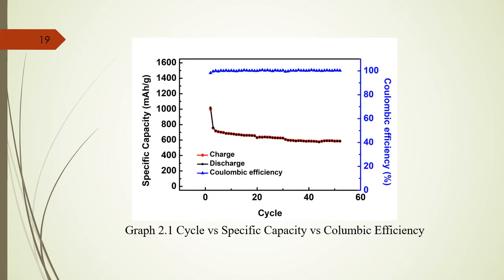So here I am presenting the results of cycle number and specific capacity in the y-axis, and cyclic stability in the x-axis, and I'm also presenting the Coulombic efficiency. So I have achieved approximately 98 to 100 percent Coulombic efficiency. So far the Coulombic efficiency is very good, and I have achieved the 1000 mAh per gram capacity. And here we can see the charge and discharge. The red color one is charge, and the black color dots inside is discharge. So for the stability we can see for almost 50 cycles it still stands at 600 mAh for the first battery.